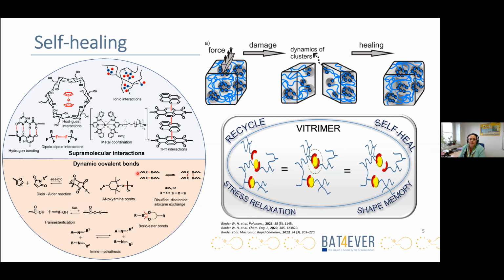In general, self-healing processes in polymer materials can occur either with or without external stimulus, so-called autonomous, and can generally be classified in two major groups: extrinsic self-healing, where the self-healing agent is embedded in a capsule or in a vascular system, or intrinsic self-healing, where we use a reversible reformation of chemical bonds within the material. Within the BAT4EVER project, we focus on intrinsic self-healing by introducing reversible bonds into polymeric materials.